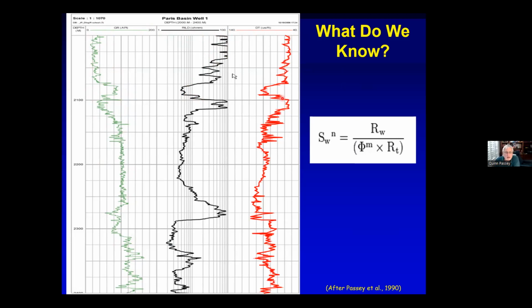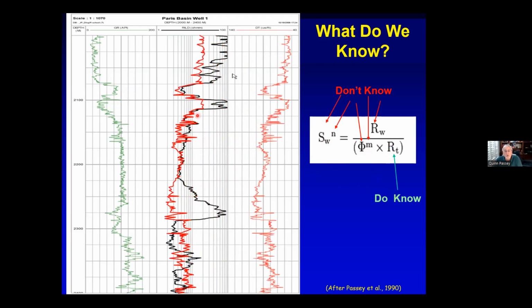And so I can take but what do we know in these shales? Well, number one, we don't know the water saturation. We have no idea what N is in the shales. We have no idea what the water resistivity is, even in unconventionals, very little produced water occurs. We don't really know what the porosity is because our porosity curve is affected by the organic matter. So all we know is what the resistivity is. And so again, in the very simple technique, we will go in and baseline in a non-organic rich shale. So we are in high resistivity. And then the organic rich shales pop out.